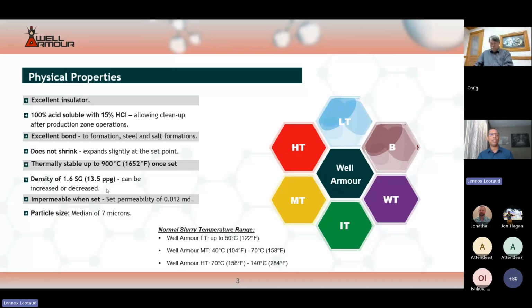We can lower that density or increase that density by the addition of other components to the blend. It is also impermeable when set. It has a set permeability of 0.012 millidarcy, and that's gas permeability. The Well Armour MT, HT, and LT components are all of a median particle size of 7 microns. So the Well Armour slurry does have a particulate fraction to it.